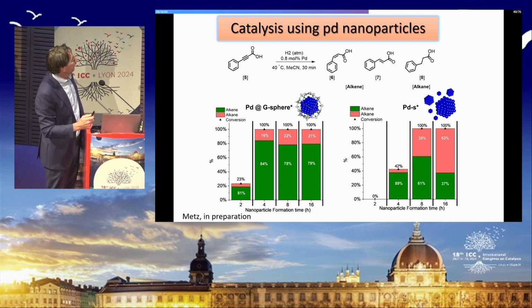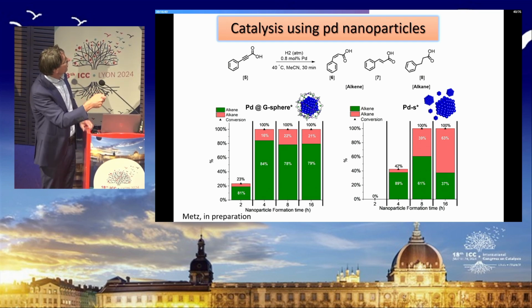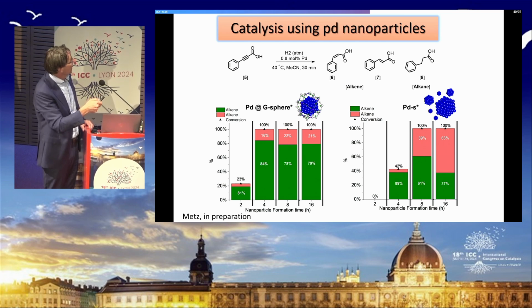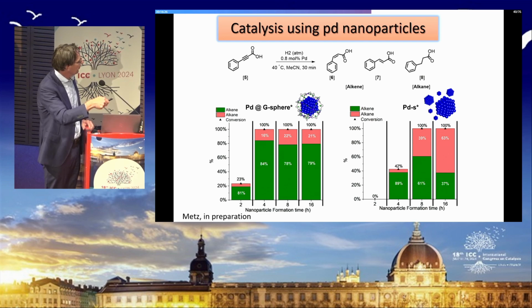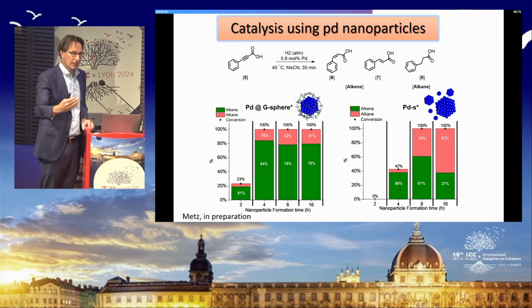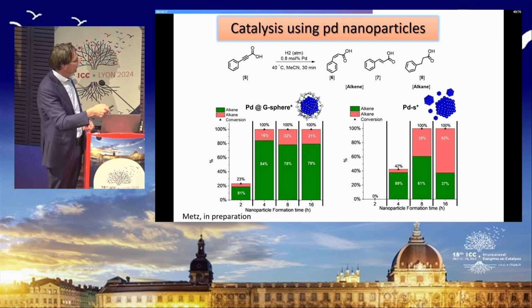So we briefly looked into catalysis. So we catalyzed this acetylene hydrogenation with these palladium nanoparticles to form the alkene or the overhydrogenated alkane. And here you see a few reactions where nanoparticle formation time is changed from 2 to 4 to 8 to 16. And with this, we have different sizes of nanoparticles.